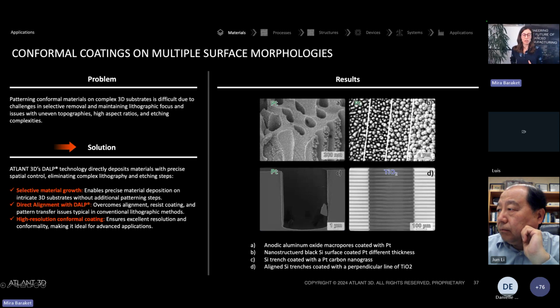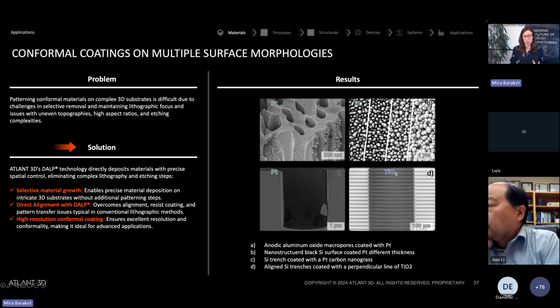As the technology is based on ALD, conformality is really one of the highest interests in the technology, but not in the same way that it is done usually. So if you were to take ALD, yes, it is very conformal, but if you were to use normal ALD on irregular substrates, on substrates that are not flat, then going through the different processes and the different techniques for creating patterns would be very troublesome, because those techniques only work well with wafers, but they don't work well when you have corrugated surfaces.